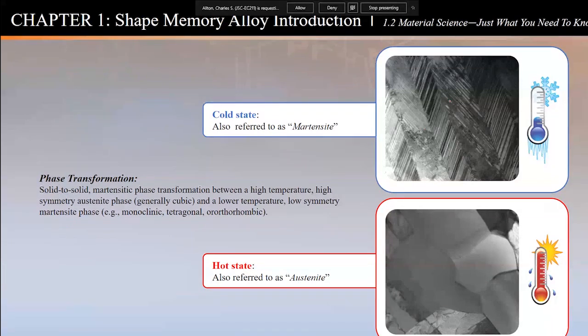And now if I take this same metal, same microstructure, and I heat it up, what happens? It goes to the higher symmetry austenite parent phase. And this is the microstructure of the same material. You can see, just like you have your conventional aluminum or steel, titanium, grains next to grains next to grains. And sometimes it's hard to believe that this is the actual same exact material, just heat and cool between them. It goes from this to this.